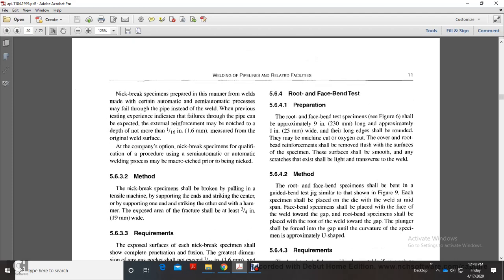5.6.4 Root and face bend test. 5.6.4.1 Preparation. Root and face bend specimens shall be approximately 9 inches long by 1 inch wide. Their long edges shall be rounded, and they may be machine cut or oxygen cut. Cover and root bead reinforcement shall be removed flush with the surfaces of the specimen. These surfaces shall be smooth. Any scratches that exist shall be light and transverse to the weld.